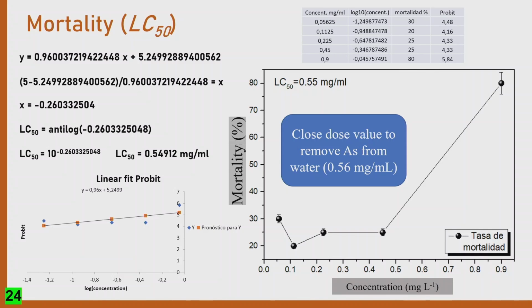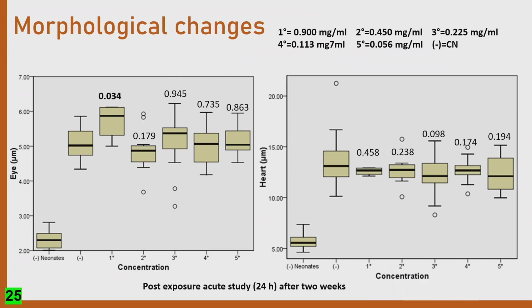And we see that the lethal dose is about 0.5 milligrams per milliliter, or just grams per liter. This is important because we compared this with the dose that adsorbs the most arsenic in our previous work, and it is really near that value. It's really close. This is good because it means that above this concentration, we can kill 50% of the population of Daphnia magna. Of course, this is not convenient for our nanoparticles.